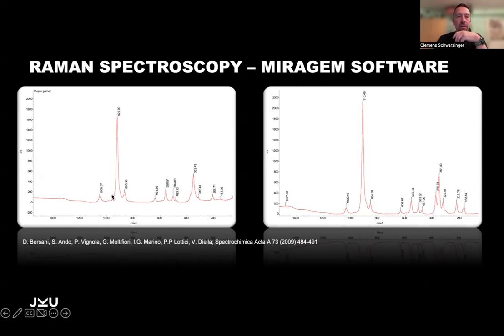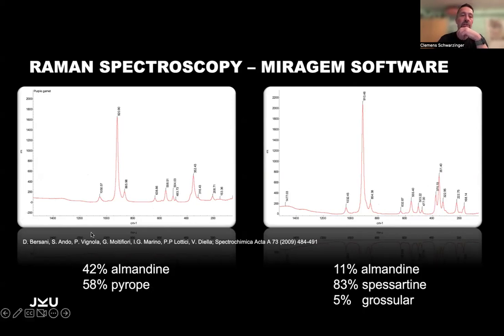You see 3 peaks here, 3 peaks here, in the middle, 1, 2, 3, 4 small ones, 1, 2, 3, 4 small ones. Here we have 3, here we have more or less only 2. So there's a slight difference. But other than this, they look very, very similar. If you do the calculation, you will find out this one has 42% almandine and 58% pyrope. The other one on the right, 11% almandine, 83% spessartine, and 5% grossular. So this one would be, by nomenclature, a pyrope, and this one would be a spessartine.